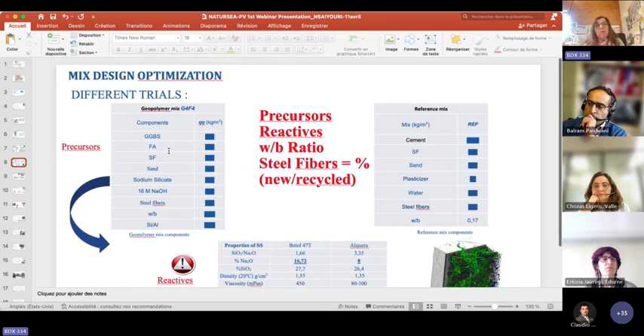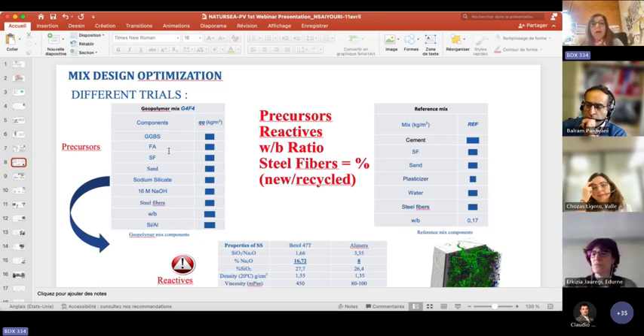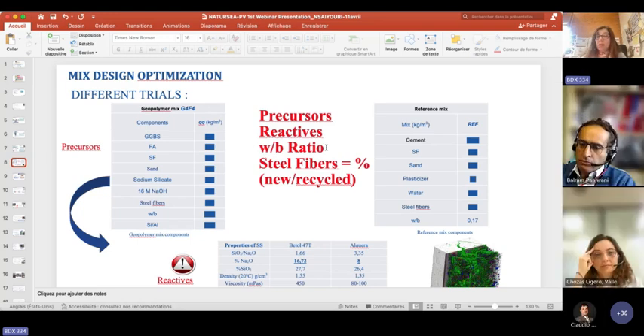So the optimization we tried was on these parameters. We have precursors, we have reactives, and the water to binder ratio. Also, it's important for all concretes, and it's important for geopolymer ultra high performance concrete also, because the more water you have, the less the strength, or the compressive strength. So we need to minimize water in the mixes. With precursors, I will not give quantities, it's confidential as in the previous presentation, but we changed for our mixes the GGBS, fly ash and the silica fume.